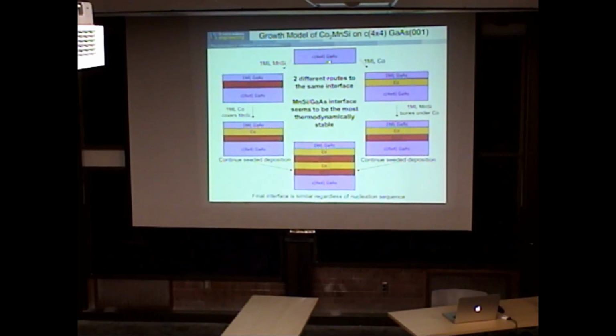Let's start off with the gallium arsenide c(4x4) surface, I put manganese silicon down. I can see from the XPS data we have manganese silicon with a little bit of gallium arsenic riding on the surface, so there is a little bit of reaction there. We put the cobalt down, and we see the cobalt goes on top of the manganese silicon, and again the gallium arsenide rides on top. So the surface energy of gallium arsenide is lower than that of the cobalt or metal. Now if we do cobalt first, the cobalt goes down, we get a bit of gallium arsenic on the surface. Put manganese silicon down, we find no attenuation of the cobalt signal. So the manganese silicon actually went underneath the cobalt.